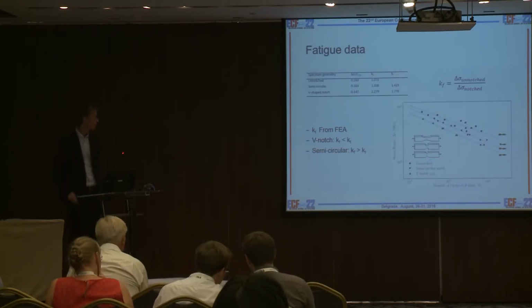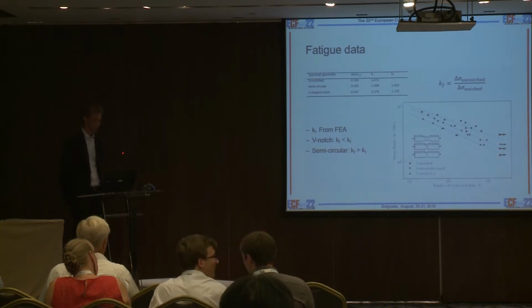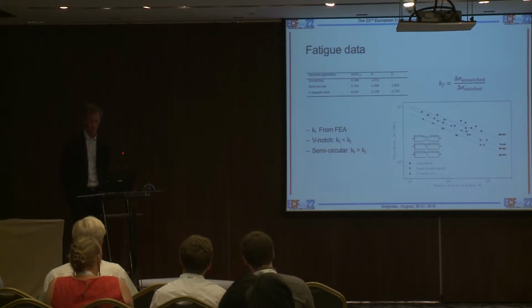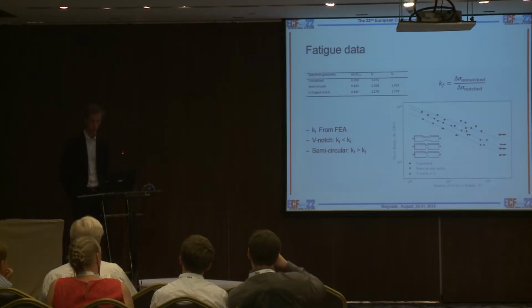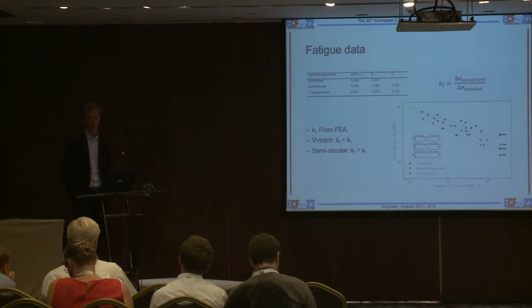Okay, so these are the fatigue data we obtained. As you can see, the unnotched specimen has a higher fatigue strength than the two notched specimens. This KT is the elastic stress concentration factor for the specimens, and we can see that there is a kind of correlation. The semicircular specimen has a higher stress concentration factor than the unnotched, of course, and also the V-notch has an even higher stress concentration, and there is a correlation in the fatigue life. However, when we evaluate the fatigue notch reduction, there is a higher fatigue notch reduction for the semicircular than the elastic stress concentration, which should not be possible, because you would have a notch sensitivity below 1. No, yeah, above 1.